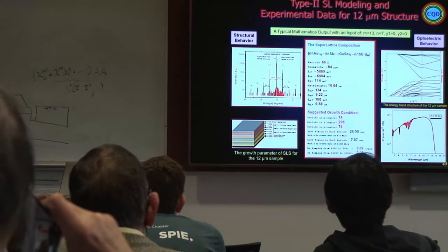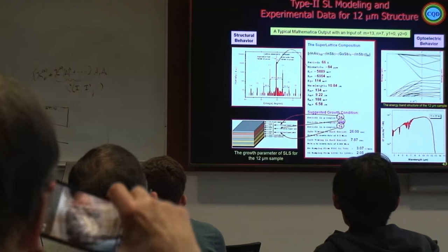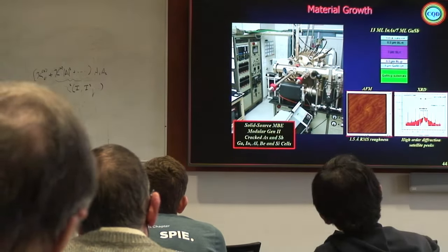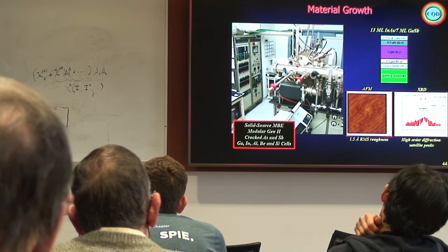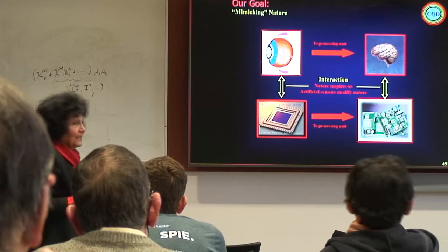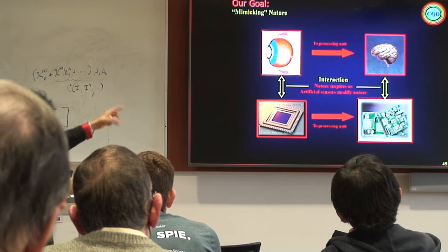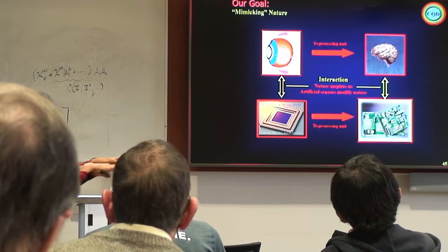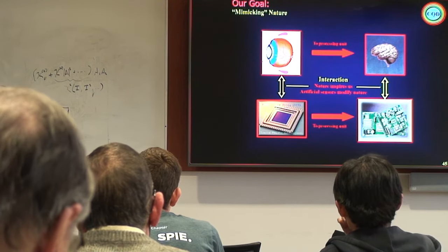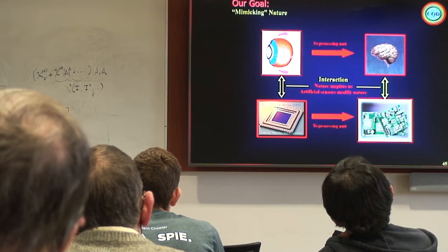As an example, any wavelength that we want on the substrate of gallium antimonide, we use the empirical tight binding model, and we can show the most important parameters that we have. After that we grow with molecular beam epitaxy, doing all of the characterization, optical and electrical, and now we're preparing the focal plane arrays. What is the preferred way to make the focal plane arrays? Artificial eyes. Equivalent of the eyes, we prepare the semiconductor material, exactly the arrays of detectors. Equivalent of the brain, we are using the arrays of transistors. It's mostly silicon, a readout integrated circuit in silicon.